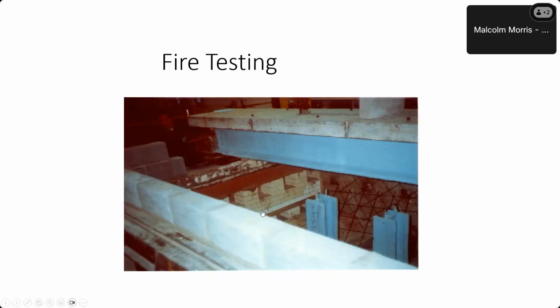That particular photograph shows what they call a loading beam test. The beam on the right hand side is actually on a hydraulic ram, so that will simulate not just the fire situation from the heat of the furnace, but actually that beam is under a defined load, so it will actually test the behaviour of the section under a loaded situation.